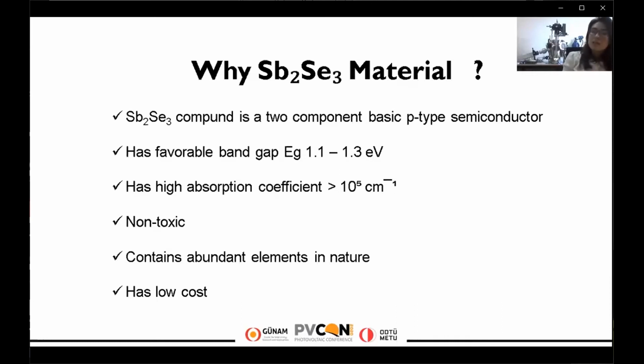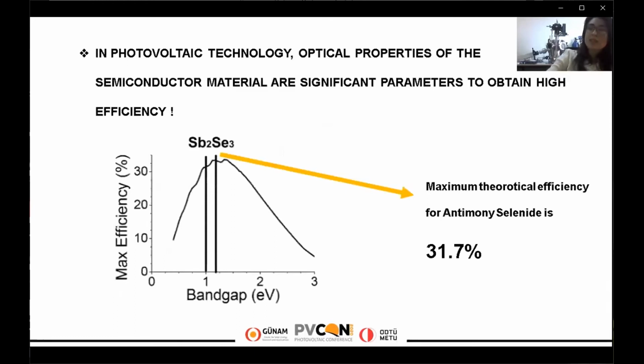But antimony and selenium, these two materials, are abundant elements in nature, and they are low cost, affordable. They are non-toxic, this is important, and they have high absorption. This compound, antimony selenide, has a high absorption coefficient, greater than 10^5 per centimeter, and the band gap is favorable, between 1.1 electron volt and 1.3 electron volt. Here we see the graph taken from Shockley and Queisser.